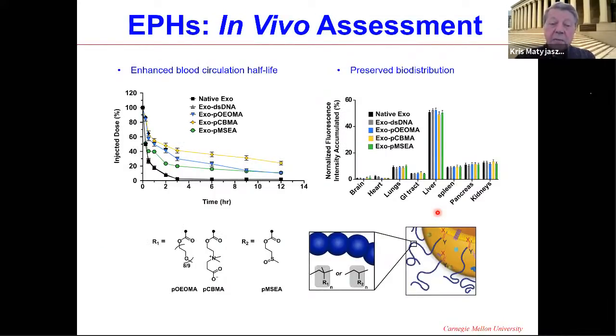So they are stabilized and circulate in blood much longer. You could see here what happens with the native exosomes and these 3 different types of polymers, with either PO side chains or this zwitterionic structure or these DMSO-like structures. Interestingly, if you look at the biodistributions, whether they are native or with 3 different types of polymers, the biodistribution doesn't change. So in that case, they can be delivered with exactly the same accuracy.